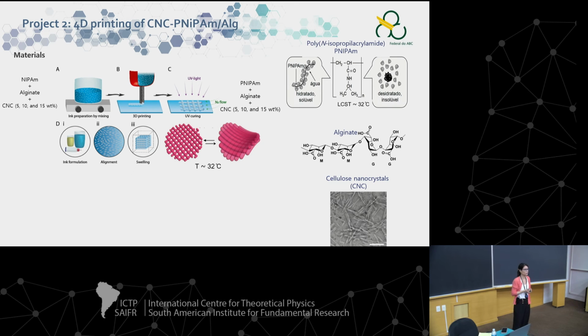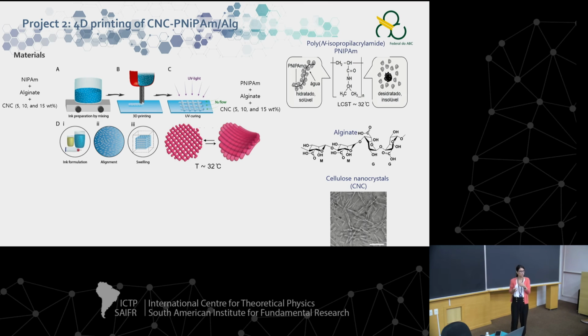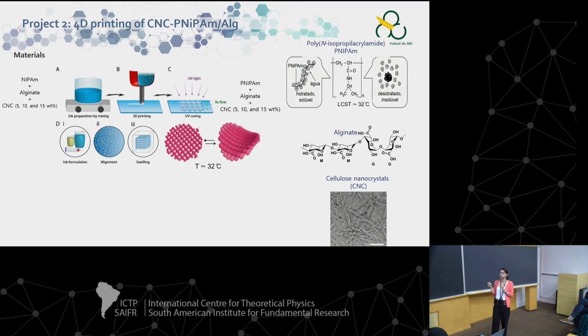So then in the second project, we work with a temperature responsive polymer, which is very well known in the field of hydrogels, which is PNIPAM. PNIPAM has a lower critical solution temperature of about 32 degrees C. At low temperature, it is hydrated and swollen, and at a temperature higher than 32, it dehydrates, so it shrinks. It is very fragile, so we need to reinforce it using another polymer, so we mixed both of them.